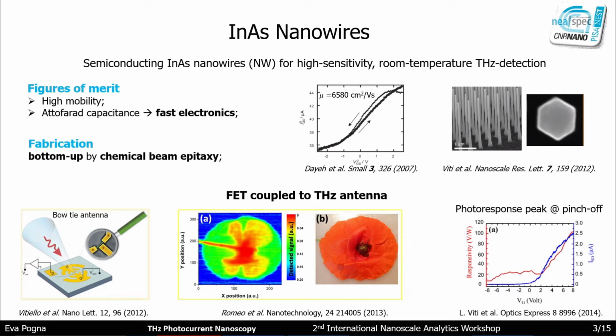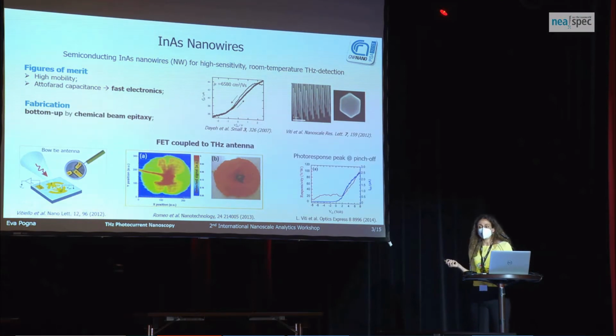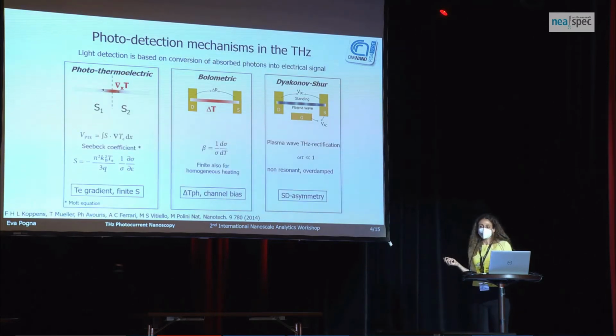And back already in 2012, they were coupled into a field effect transistor and a bow tie antenna to couple with the terahertz radiation in the far field, and demonstrated interesting noise equivalent power that even allowed to perform far field imaging with the nanoscale detectors. Interestingly, the responsivity of these detectors depends strongly on the carrier density. But what was the mechanism at the base of their ability to work as an efficient terahertz radiation detector, even at room temperature, was still debated and unknown. So here comes our study.